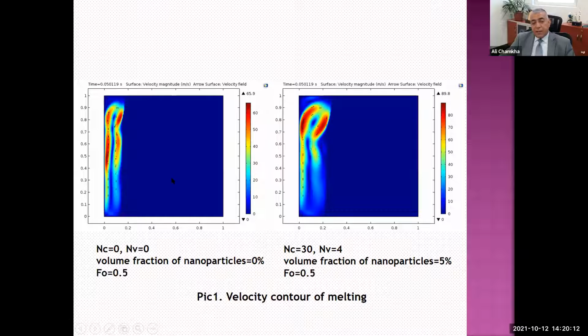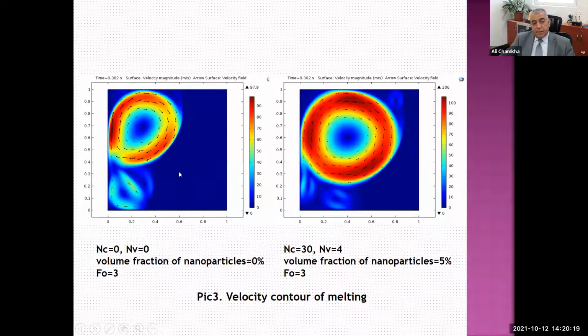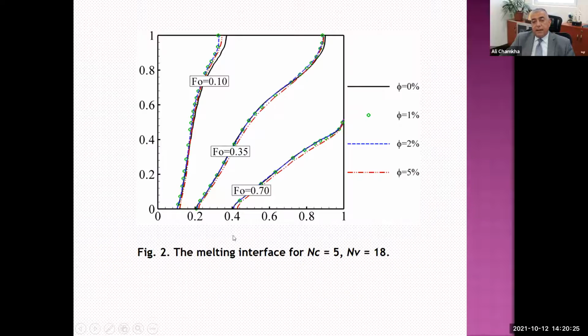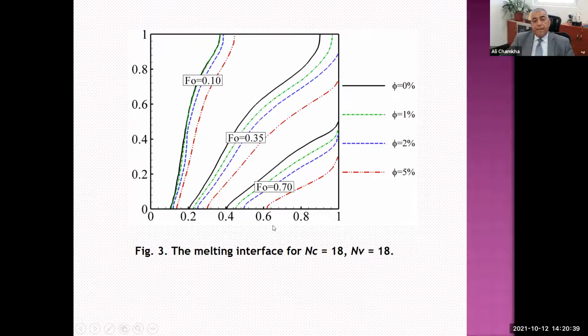Now here are some pictures, taken with the same colors, for the base fluid without nanoparticles, and here with nanoparticles. And here you can see the melting interface that you saw as you are moving in the direction of melting. And this is for different volume fractions, 0 volume fraction, and so on. Same thing here.